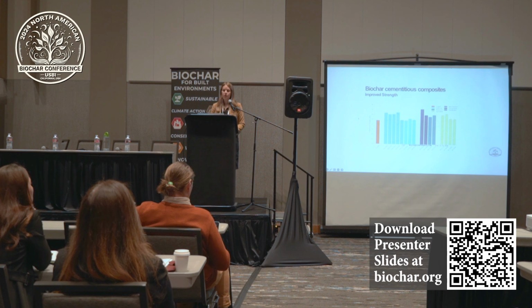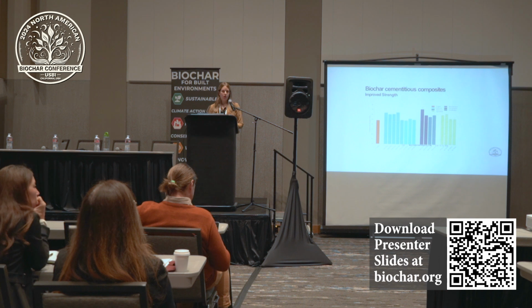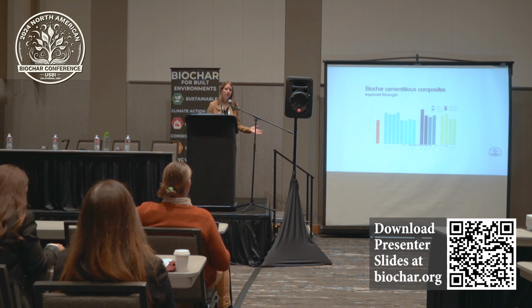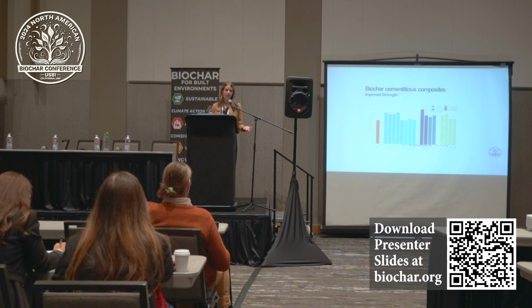So we've looked at hardwood feedstocks, softwood feedstocks, agricultural feedstocks, and as you can see across the board, different pyrolysis conditions, we are getting pretty good properties with the concrete. And I wanted to point out also that this is with 10% cement replacement with biochar. Why 10%? Really, it's because the sources of biochar we had were pretty varied in how much quantity we had, so we wanted to test them all at the 10% level so we could be consistent.